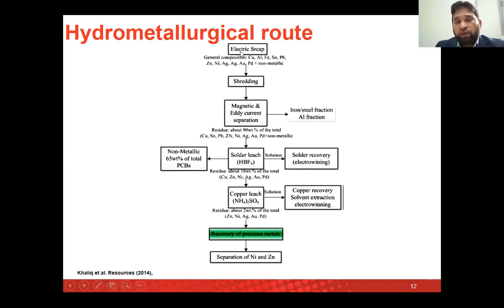Okay, so first of all, when we have the electric scrap, this scrap will contain copper, aluminium, of course, iron, tin, lead, zinc, nickel, gold, silver, palladium, and non-metallic components. We need to size this electronic waste, to shred it. After shredding, we do the magnetic separation and eddy current separation steps, because you cannot do the acid treatment of all of that material. That's not useful, because a lot of material can be separated at the early stage.